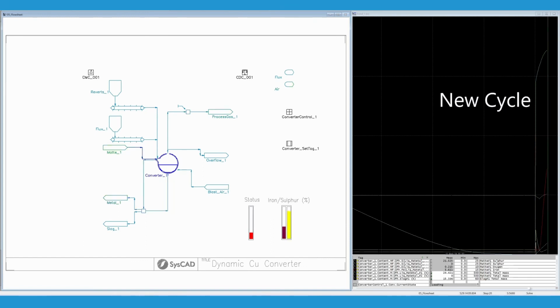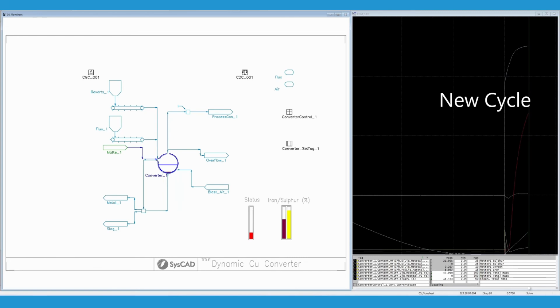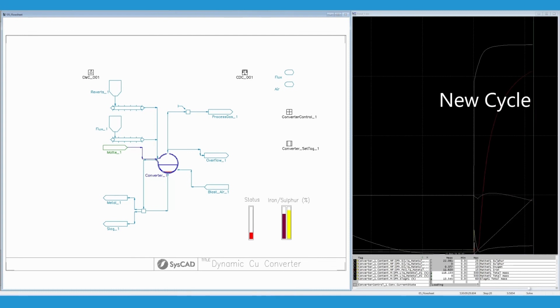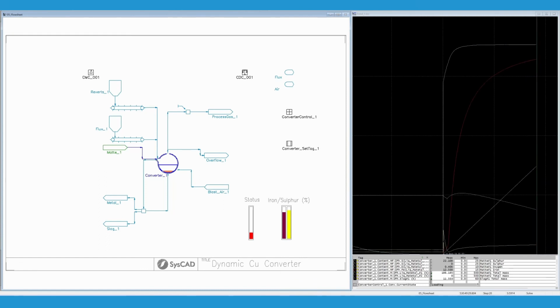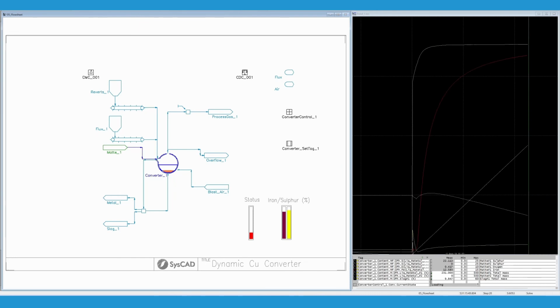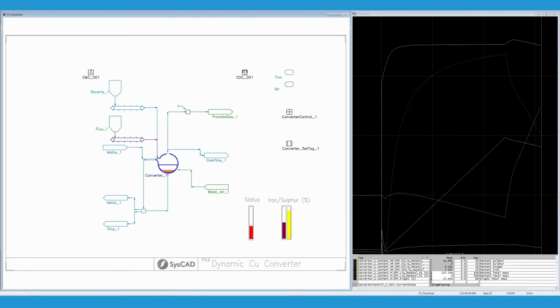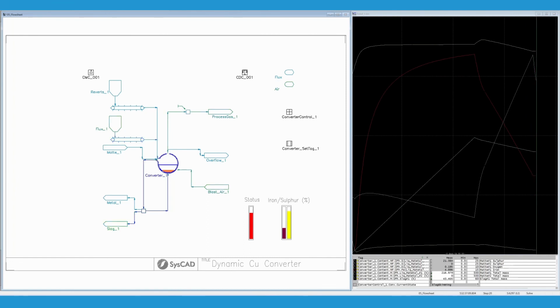A possible enhancement that can easily be added to the model is the use of constrained free energy to oxygen in gas to limit the extent of equilibrium of oxygen, especially towards the last stages of the sulfur removal, where mass transfer limitations might start to become the rate limiting steps. At the end of the copper blow, about 14 tons of oxide are produced, which is consistent with industrial experience. Some of the residual oxide is washed or redissolved at the beginning of a new cycle, where 3 new fresh matte ladles are added. The process is then repeated.